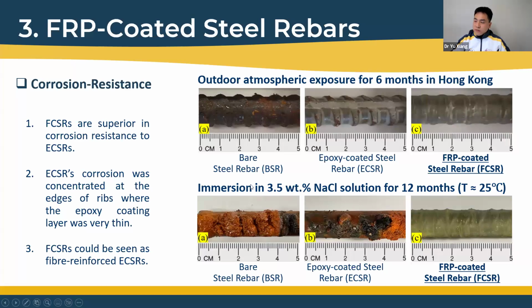We then placed the three types of rebars in sodium chloride solution as a simulation of seawater for 12 months in the laboratory. The FRP coated steel rebar also remained in a very good state, while the other two rebars corroded seriously. These observations confirm that the FRP coated steel rebar has superior corrosion resistance in the laboratory environment.